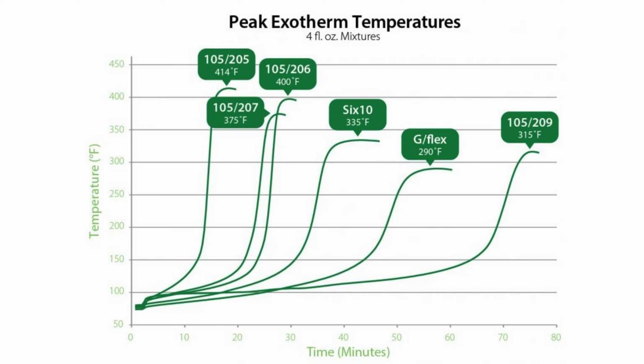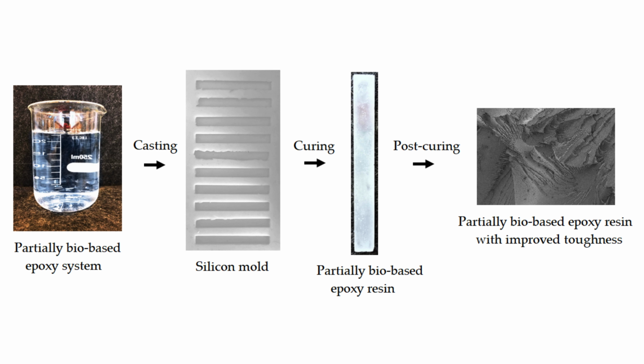An exothermic reaction occurs during the curing of epoxy adhesive systems. Exotherm is the heat that is self-generated by the curing reaction. If the exotherm is not controlled, it can lead to greatly reduced working life and even to a dangerous situation where the exotherm can be great enough to cause combustion. The exotherm can be minimized by reducing the reactivity of the mixed components and by limiting the batch size.